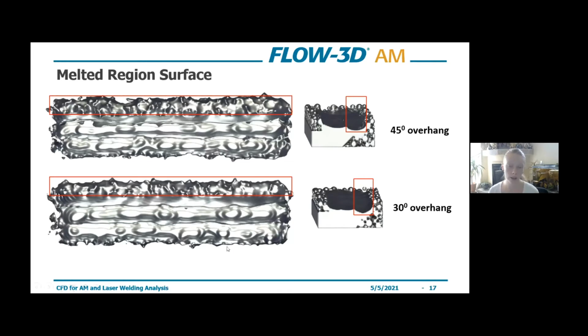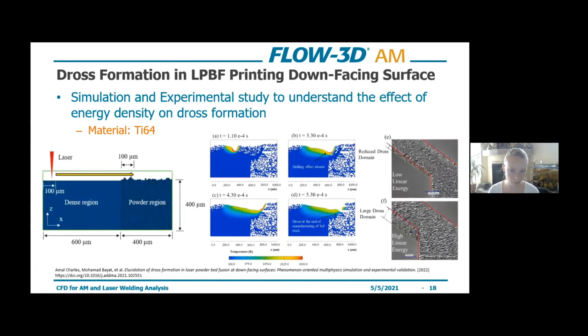And so you can see in the comparison of the two here that the 45-degree angle did lead to more surface roughness, lack of fusion, while we get better conditions for the 30-degree overhang, which depends on how much flexibility you have in your design. But there's things that you can analyze from a modeling perspective without having to make these parts out every time.